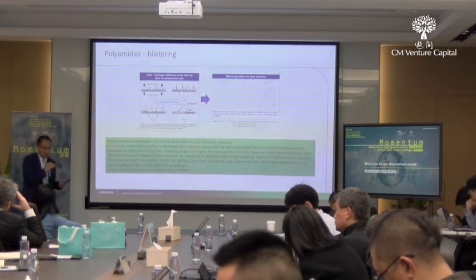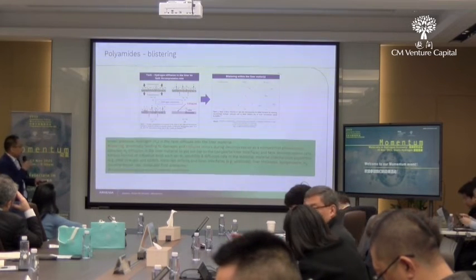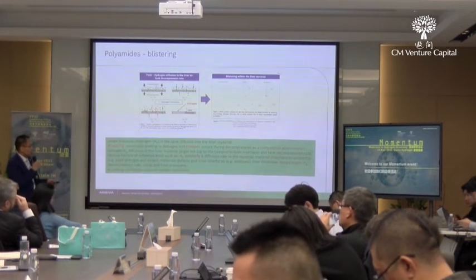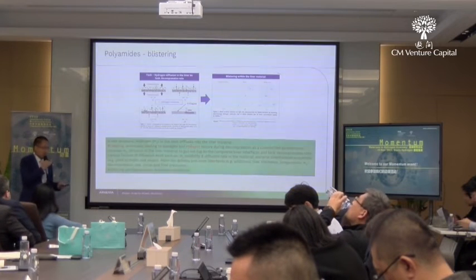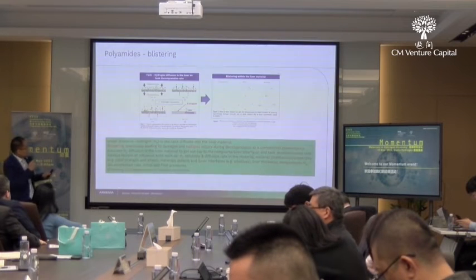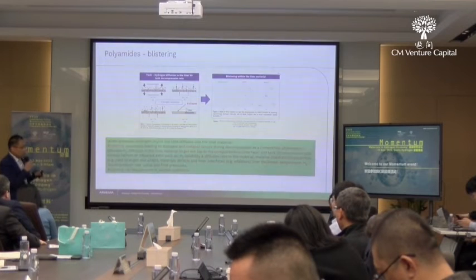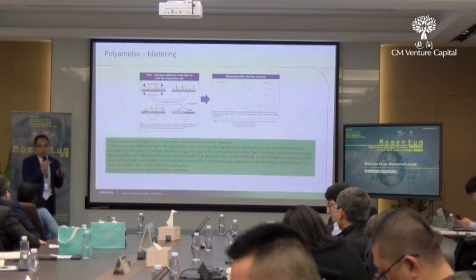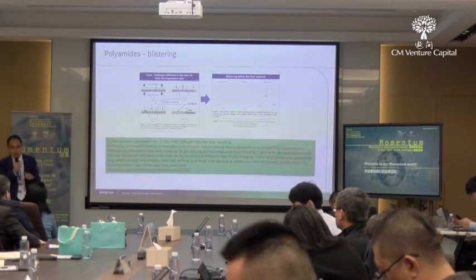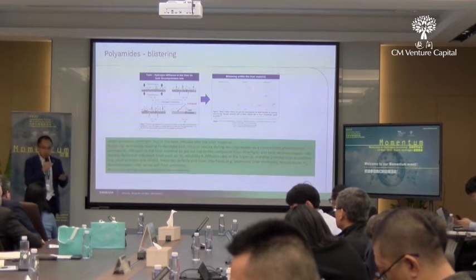So today I will talk more about the blistering. You can see the blistering is impacted by the material itself, like the different solubilities, diffusivities, and the permeations. These generate the matrix for the blistering behaviors. As well, you can see the decompression speed ratio is also important. If you go at a very rapid speed, it is more likely to create more risk of blistering.